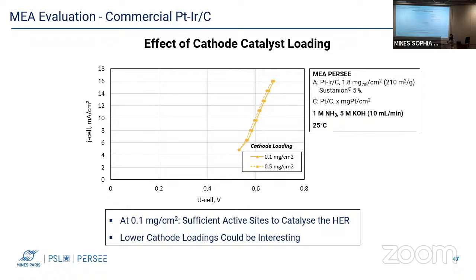No effect on the performance of the MEA was obtained within this range. This means that at a loading of 0.1 milligram per centimeter square, we could have a sufficient number of active sites in order to catalyze the hydrogen evolution reaction at the cathode, and it could be interesting in the future to try loadings lower than 0.1.